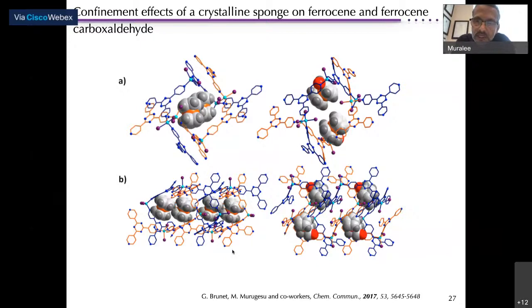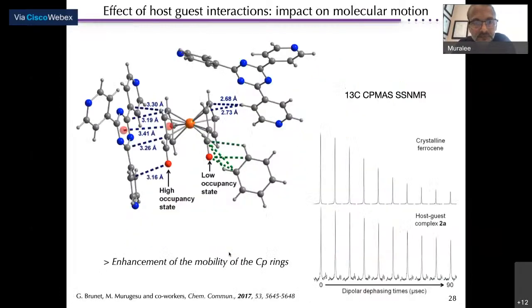Although Fujita reported that you have to activate the MOF first, I can tell you for this case you don't need to. The solvent, nitrobenzene, comes off without even activation the moment you start soaking. So it is a much milder approach than activating the MOF first.